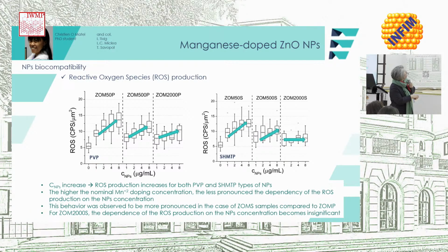But the higher the nominal manganese doping concentration, the less pronounced was the dependency of this ROS production with the nanoparticle concentration. I put some arrows here in order to be more visible. And this effect, this behavior was more pronounced in the case of ZOMS category of nanoparticles or surfactant. And in fact, for the highest manganese concentration, you see here that it was practically no more dependence of the ROS production on the nanoparticle concentration.